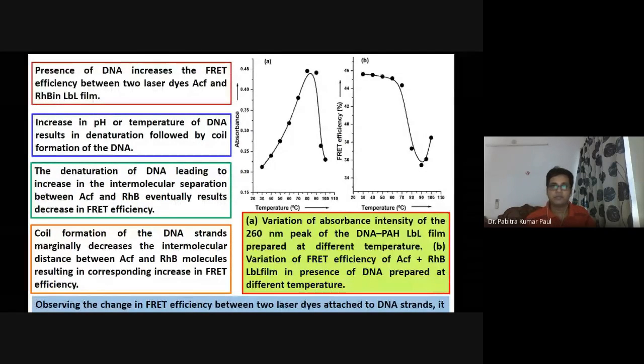because when we add DNA in the presence of the two dyes, it eventually decreases the distance between the dye molecules. An increase in pH or temperature results in denaturation, followed by the coil conformation of DNA. So at very high temperature, 95 degrees centigrade, and high pH, about 13, the hydrogen bonds between the base pairs can break, and ultimately the DNA is denatured and becomes single stranded, and finally becomes a coil-like structure, because that is the entropically favorable structure for the DNA under that condition. So the denaturation of the DNA leads to an increase in intermolecular separation between Acf and RhB, and that's why the FRET efficiency decreases.